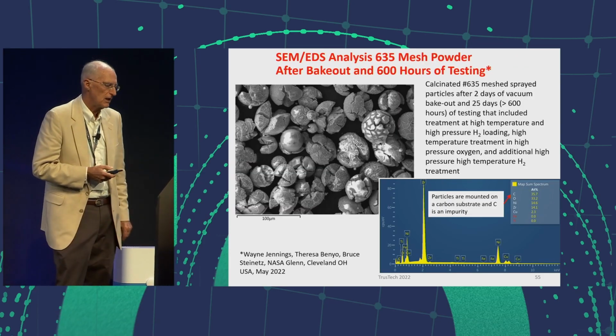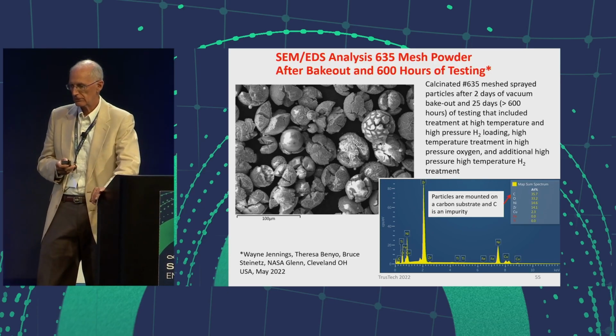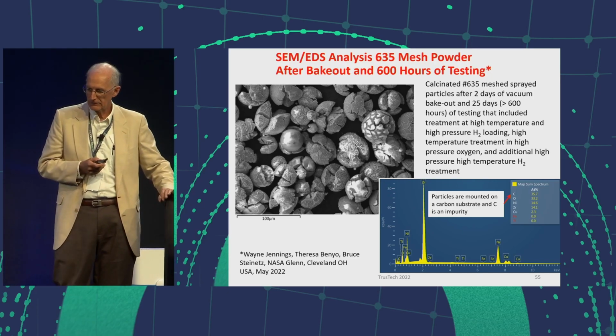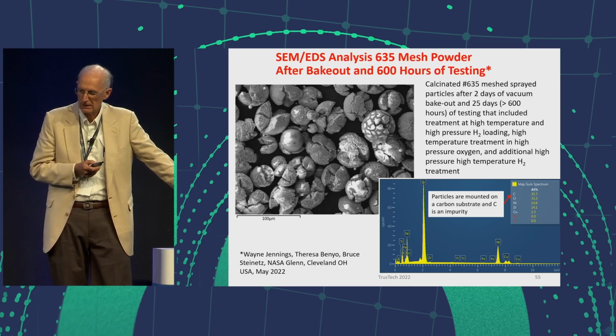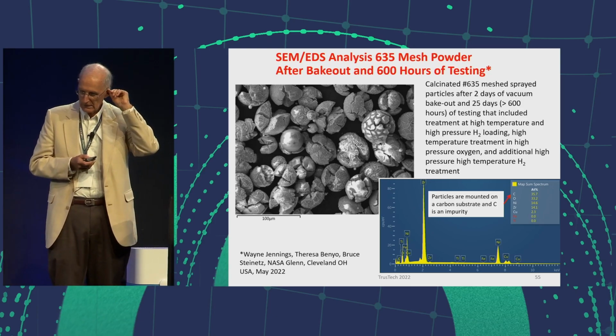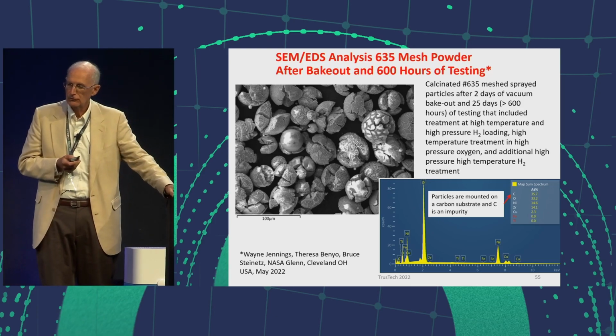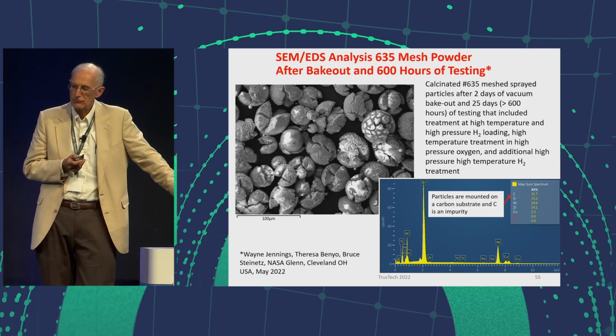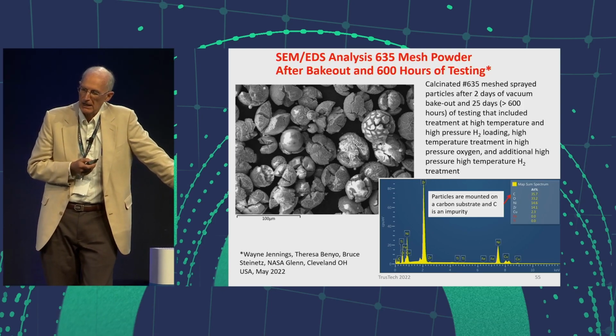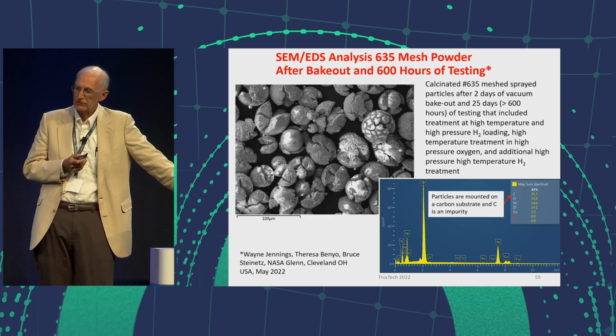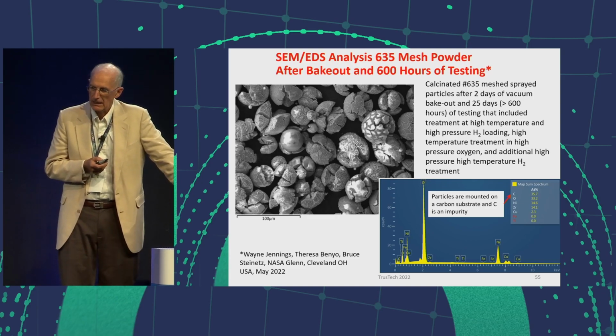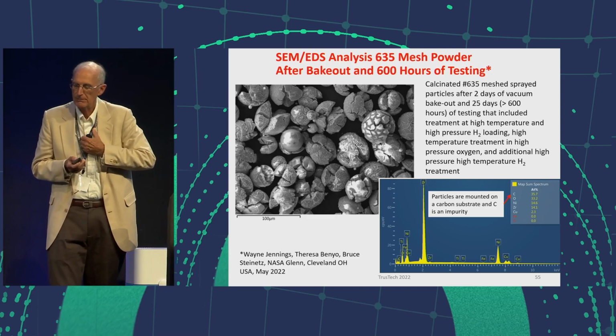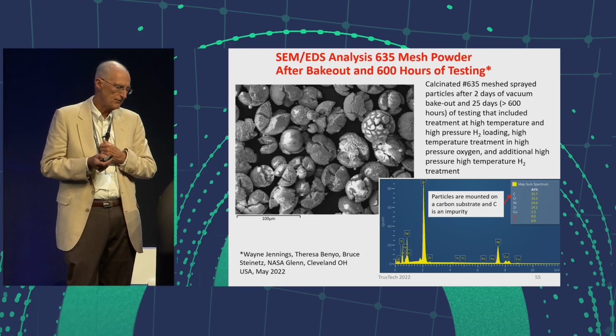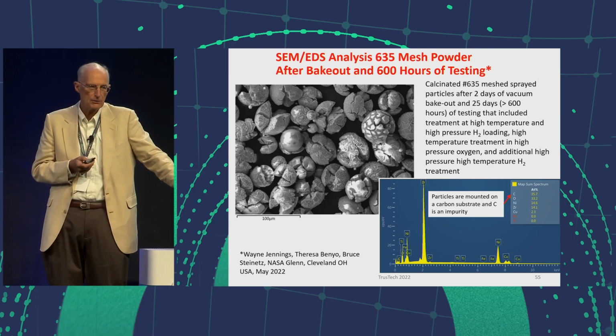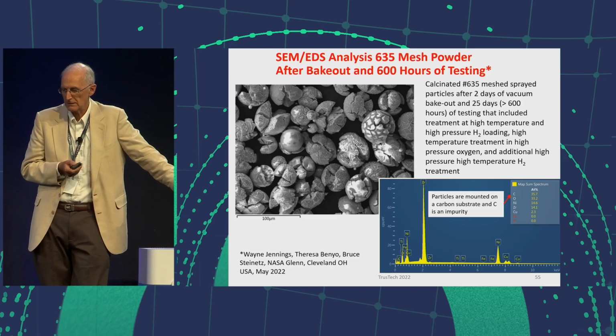Now, I got this slide just a few days before I put this talk together. And again, this came from Wayne Jennings at NASA Glenn. So this is an electron micrograph on the left of the particles after the 600-hour test. And you can see they're still broken up. And one thing I want to emphasize is you don't see any pitting or craters on this thing that you might see in a situation where you had excess heat.